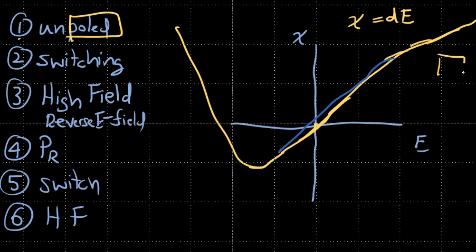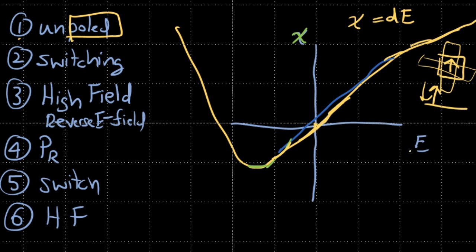Consider our piezoelectric block material oriented with polarization pointing up. A positive electric field increases the strain. If you apply a negative electric field, you get compressive — negative — strain. As we keep decreasing the electric field, eventually the polarizations switch. At that switching point, the effective D coefficient is essentially zero: you're applying a field but getting no net change, because some domains are compressing while others are switching, which cancel out. This plateau is the switching region, also known as the coercive field region.